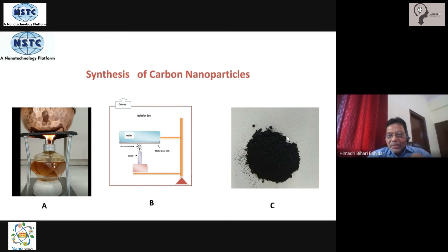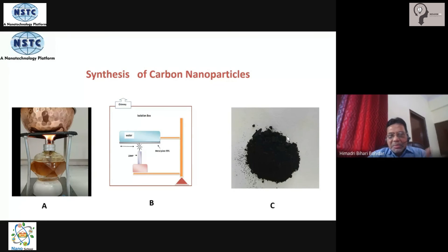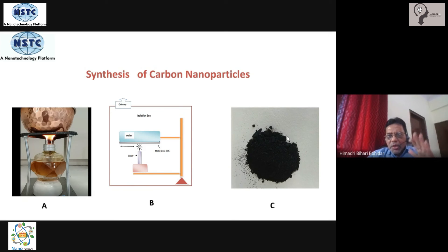All other carbon nanomaterials — graphene, nanotubes, multi-walled nanotubes, fullerenes, carbon dots — are prepared at much higher temperatures and much harsher conditions compared to this. This material is prepared at low temperature, not exceeding 150 degrees. The flame may reach 250–300 degrees, but the metal surface temperature stays close to that of water, around 150 degrees maximum. You get this amorphous powder, the nanomaterial, at essentially zero cost — you haven't spent any money making it.